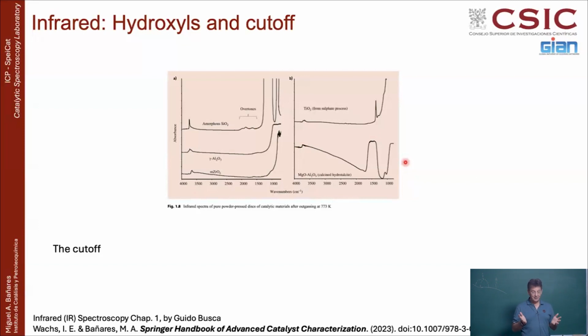What is a cutoff? Well, infrared is very, very sensitive. If you have things that absorb a lot, it will saturate. And the problem is that the oxide supports tend to absorb quite a bit, especially below 900 wave number. And that is a problem. You see a cutoff here, it saturates. You see 1000 and below. 900 plus, you can still see something. Forget, this is zirconia, alumina, silica. That is a problem because most of the supported oxides characteristic vibrations will be at 1000 and below, and you cannot see.